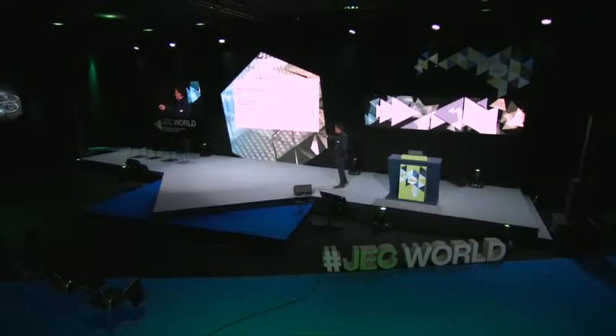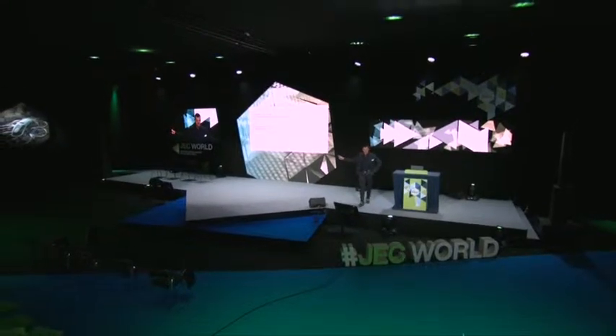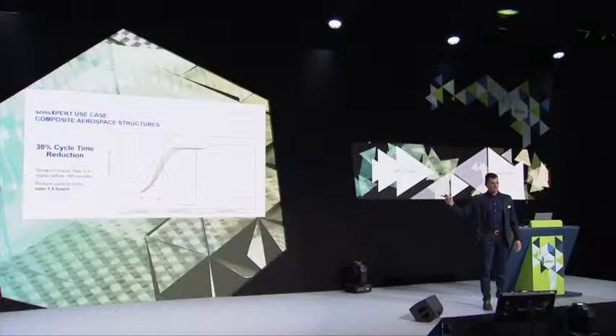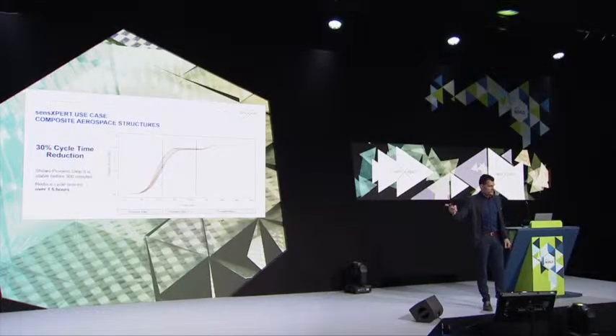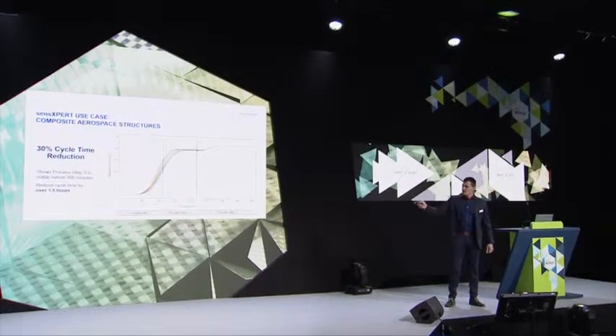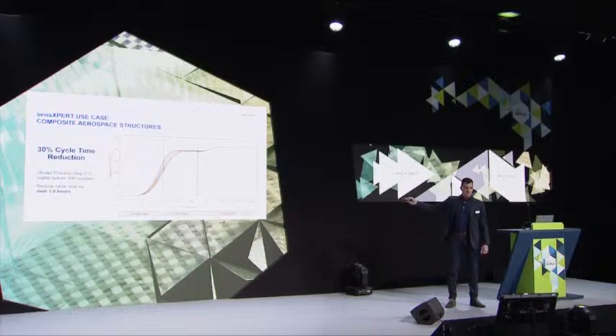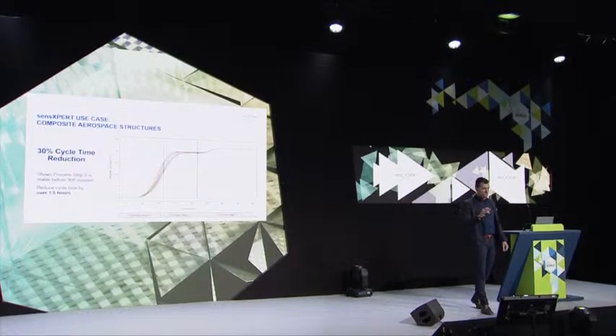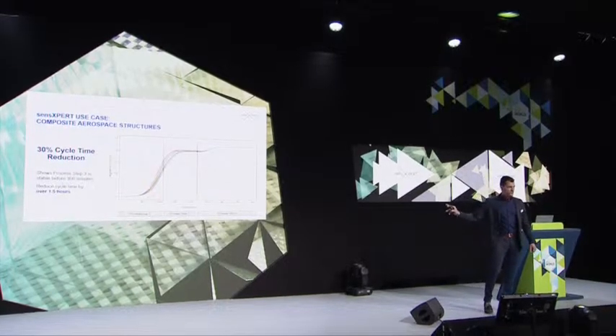What happens here? We have a material deviation in the RTM process, and that is huge if you look to the scale on the left side. We talk about a variation in the degree of cure of 20% in this first reaction step. If you follow the entire curve, then you follow the real manufacturing protocol this customer is using today.